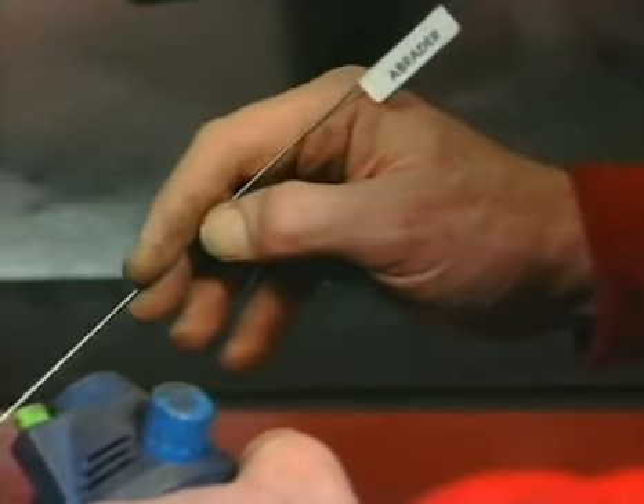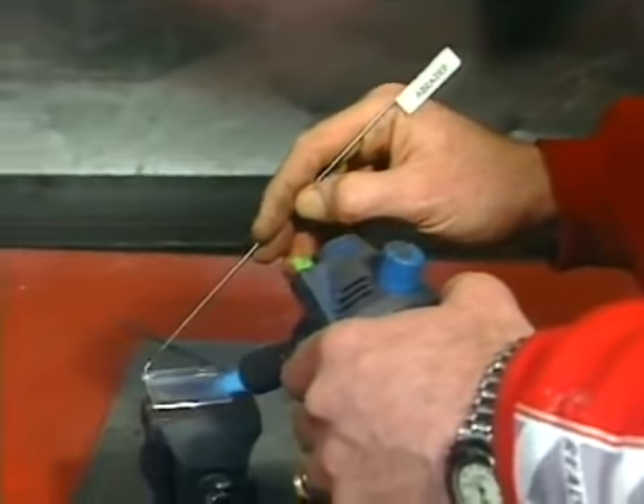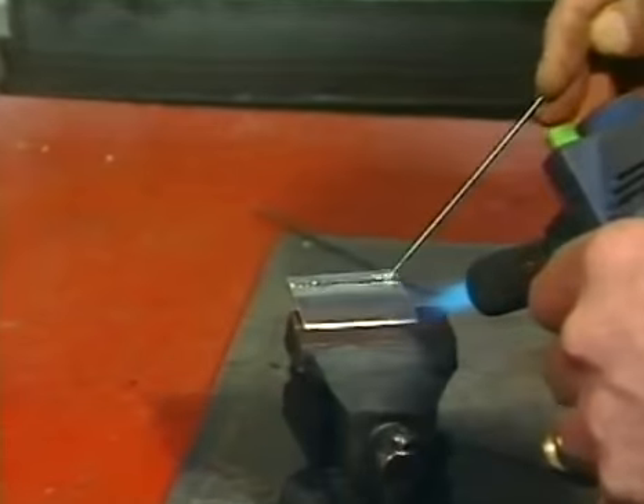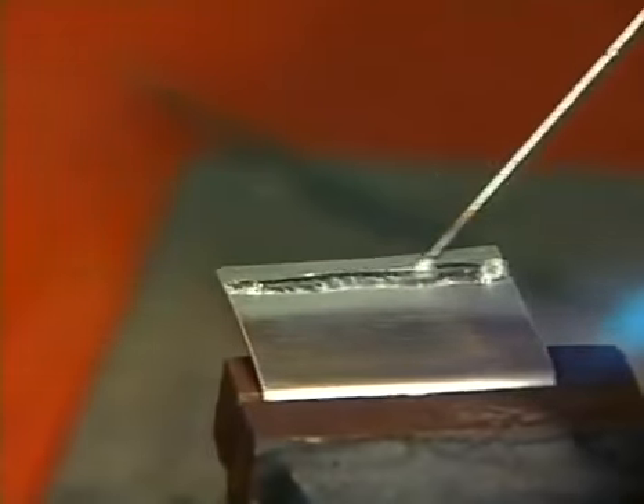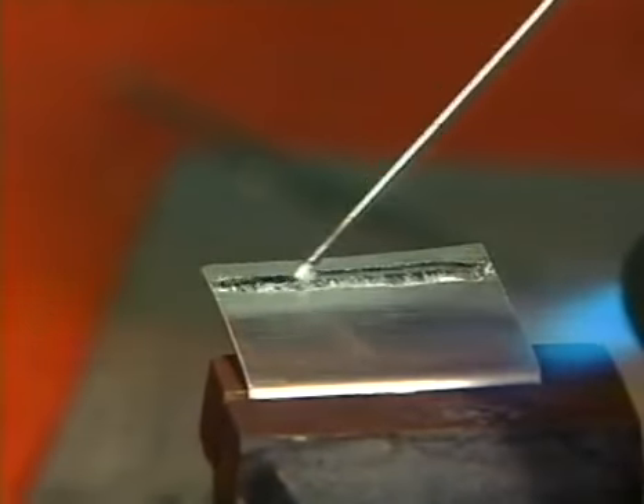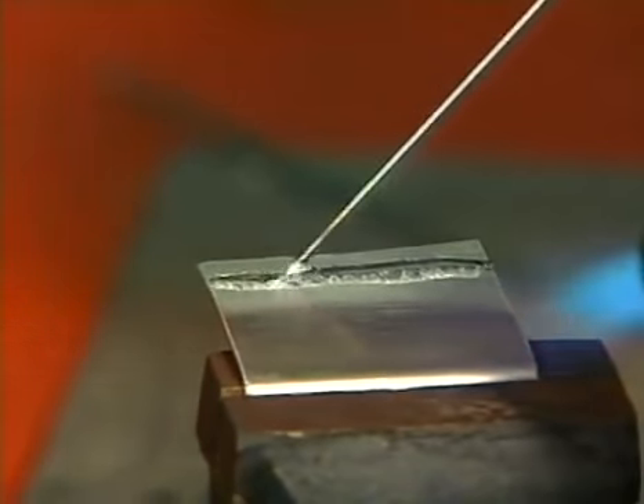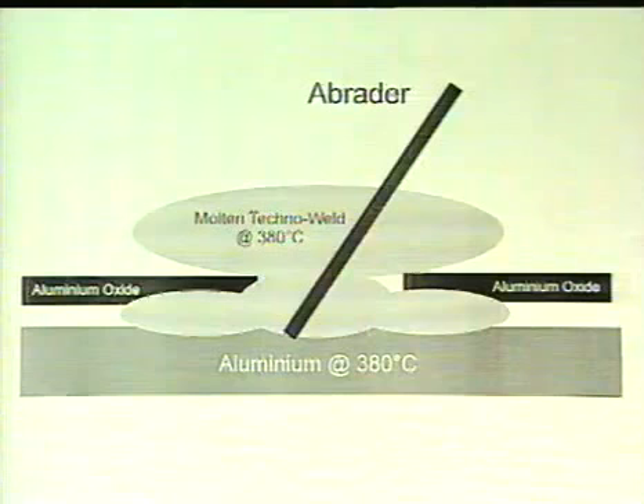The aluminium oxide is very hard, so we break through the oxide layer by scratching through the molten Technoweld with a stainless steel abrader. Once the oxide layer is just slightly broken, Technoweld gets onto the aluminium, and magnesium in the Technoweld rod splits the oxygen off the aluminium oxide, depositing aluminium, leaving the oxygen free.